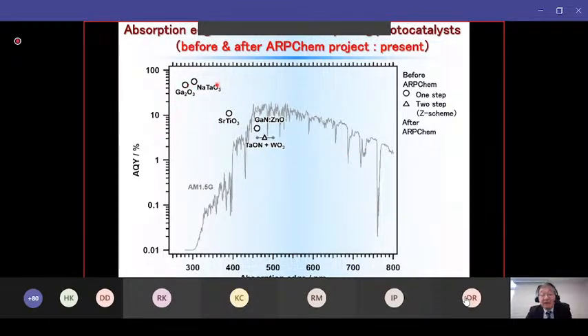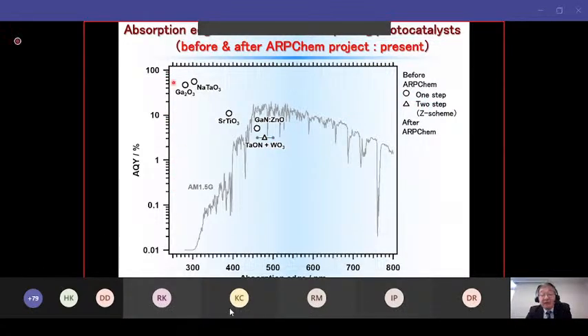Here I show the photocatalysts which are able to split water into hydrogen and oxygen. This circle shows the one-step overall water splitting reaction. This triangle shows the two-step overall water splitting reaction. And this axis is apparent quantum yield in a logarithmic scale. And this is the absorption edge of the photocatalyst.